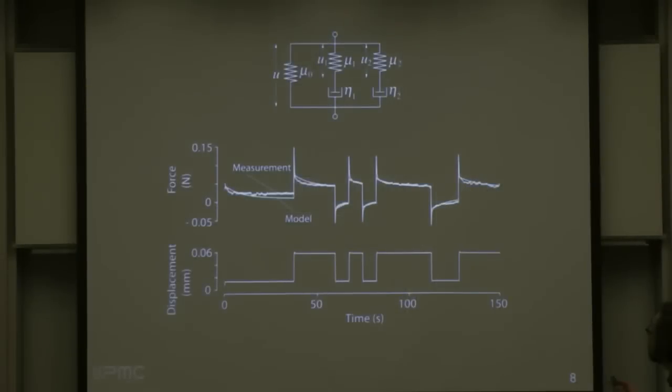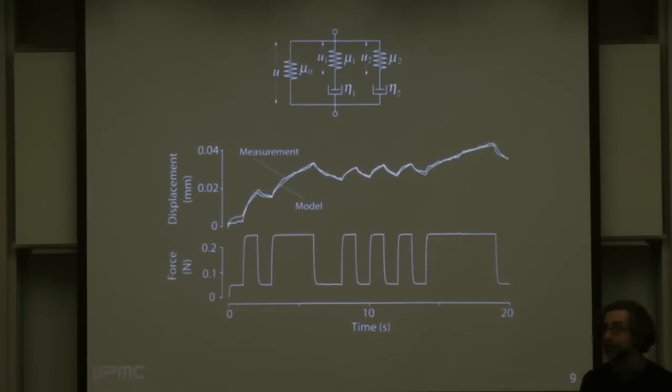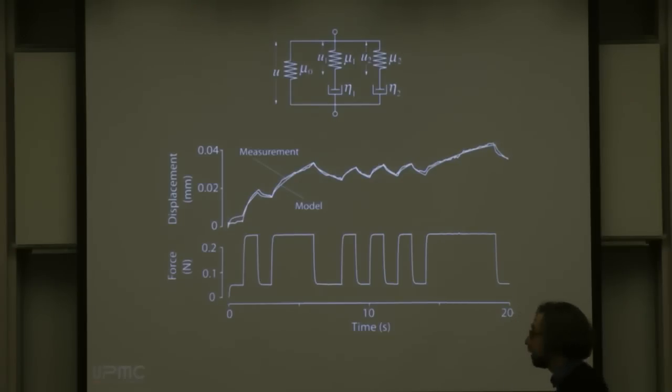So what is their role in terms of sensing or manipulation? Again, you certainly could attribute some benefits to having these different time constants. It is known that the neural equipment sitting behind also has different time constants, so it might be well tuned to take advantage of the mechanics of the skin. So this three-parameter model is a good representation of what you have in your fingertips. And of course, we replicated the experiment in the opposite causality, which is to load the skin with a known force and then see how it moves. And that's what you see. It creeps along as you load it.